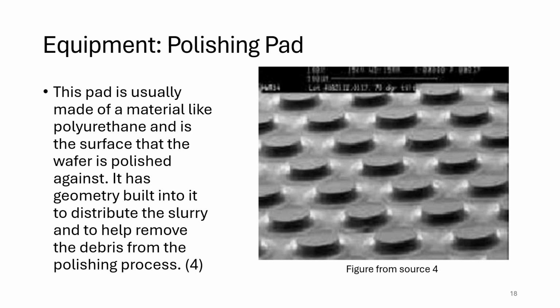Pad state changes with use. Without conditioning, pads glaze and material removal rate slows down. While on the other hand, over-conditioning can increase scratches on the wafer surface. That's why pad life, conditioning rates, and groove design matter for stable material removal rate and minimizing defects. A pad that's monitored and well characterized helps to give the manufacturer a consistent behavior from wafer to wafer.